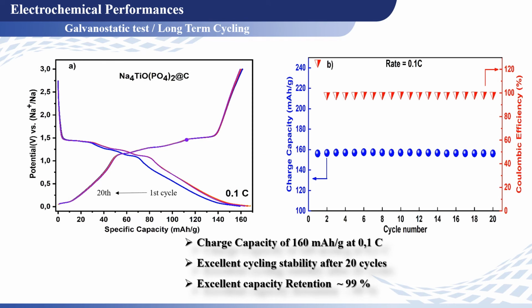The following tests are galvanostatic and long-term cycling tests. As we can see in the figure of the galvanostatic test, our material exhibits an initial charge capacity of 160 mAh per gram at a current rate of 0.1 C. Also, one reversible plateau during the charge and discharge between 1.54 volts and 1.1 volt is observed, which is in good agreement with the CV results that we saw before. Also, our material shows an excellent cycling stability after 20 cycles and excellent capacity retention approaching 99%.